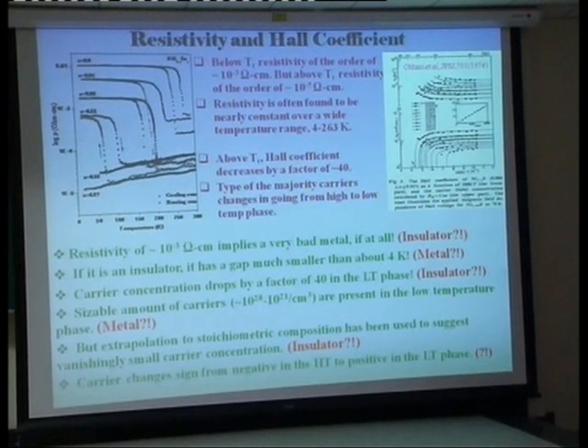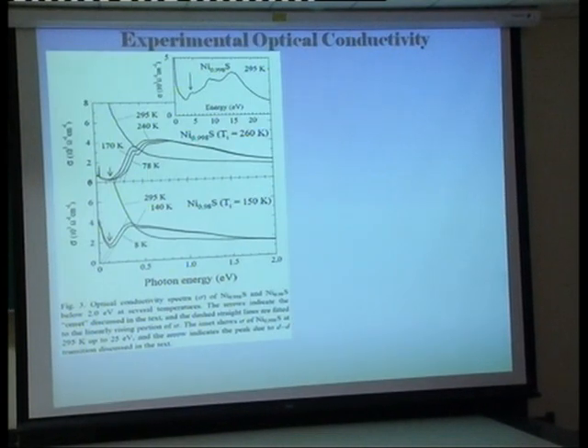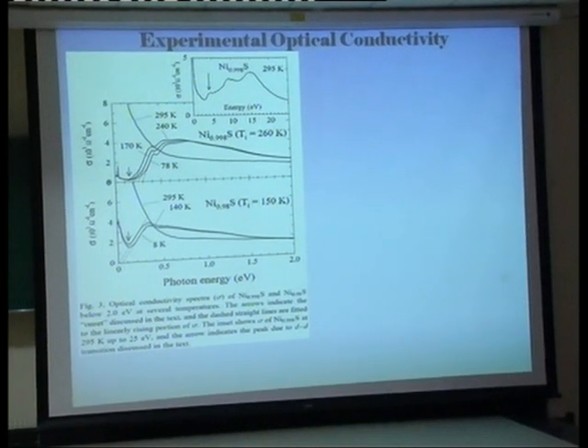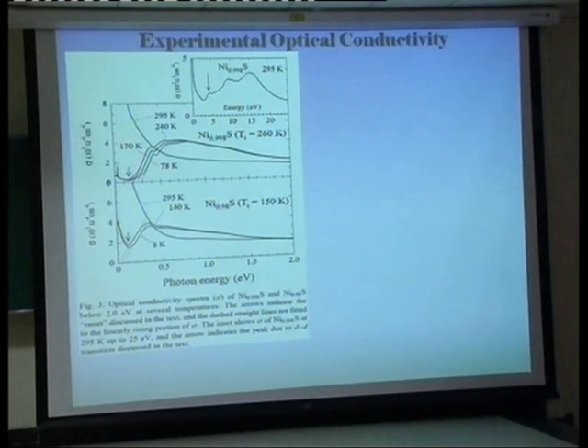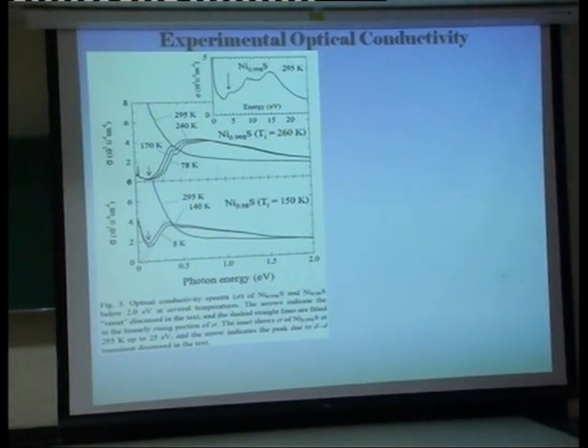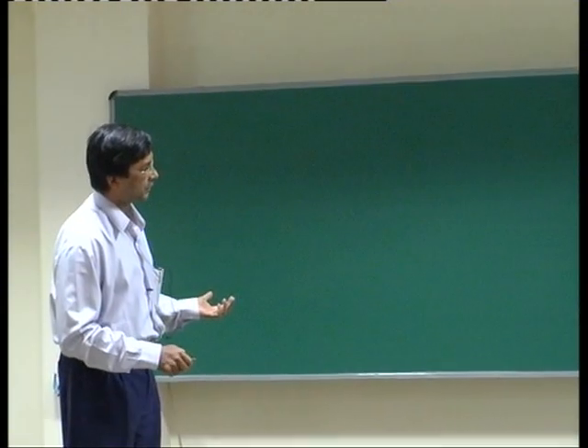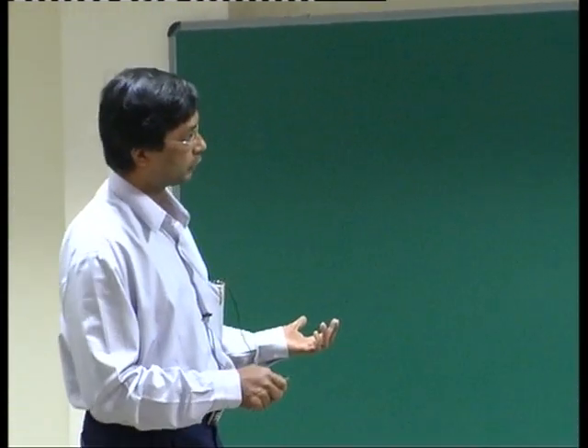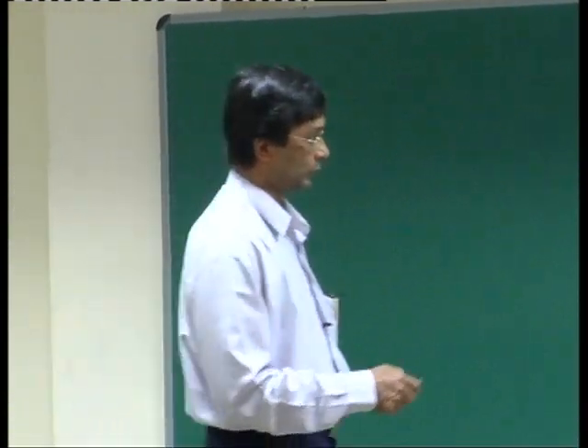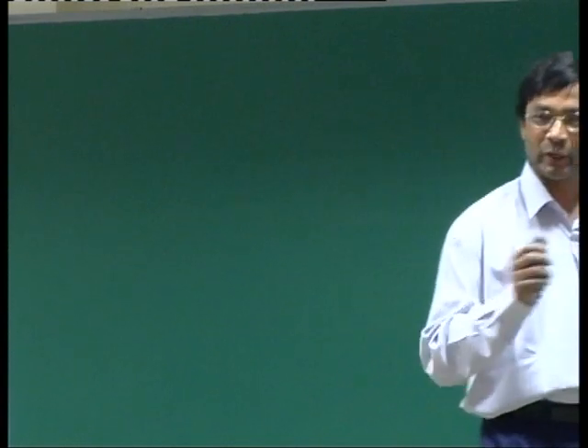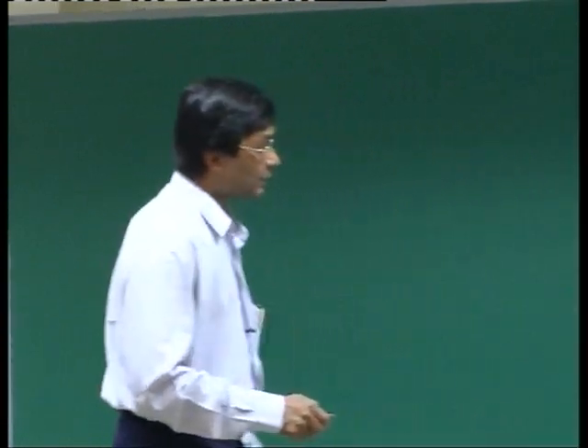So this went on, and then of course one would think that we should be able to get the idea from spectroscopic data. There are two kinds of spectroscopy that we can do. One is the optical conductivity, and that was of course done. The optical conductivity is shown over here. This is the high temperature phase that I keep telling you I'll not talk about, and I'm mentioning I'll not talk about it. That's the boring metal. So this is the low temperature phase for a certain concentration of nickel vacancy.